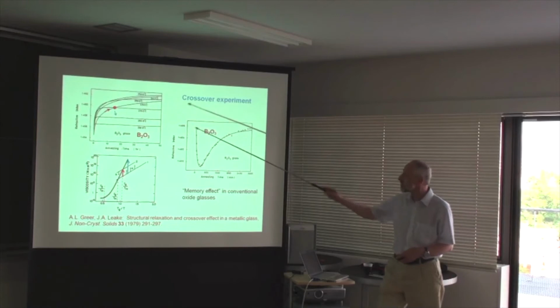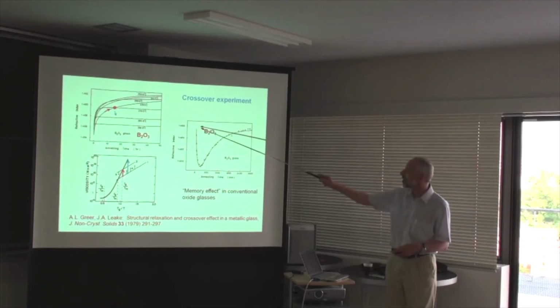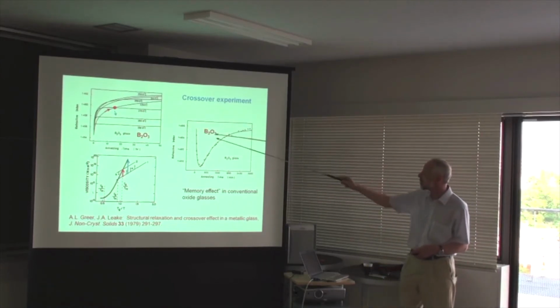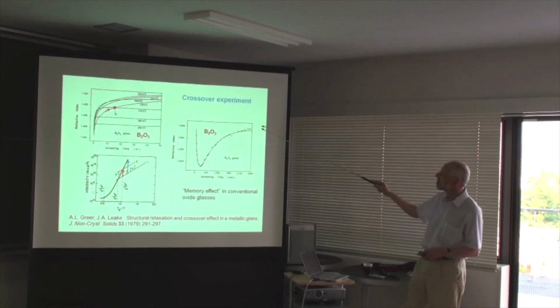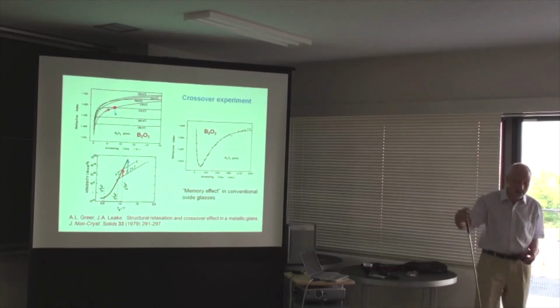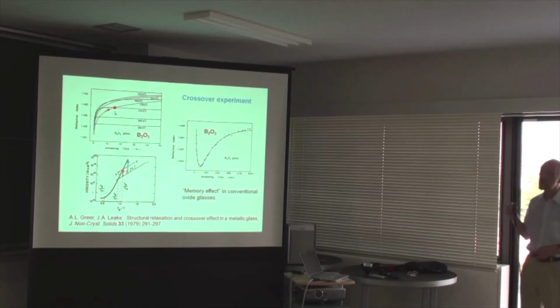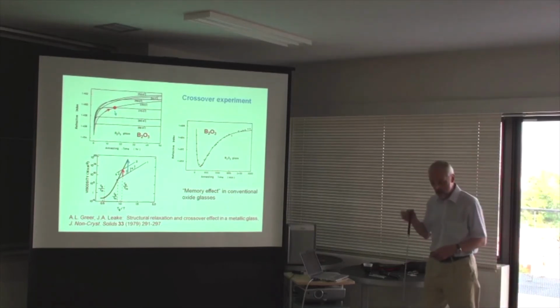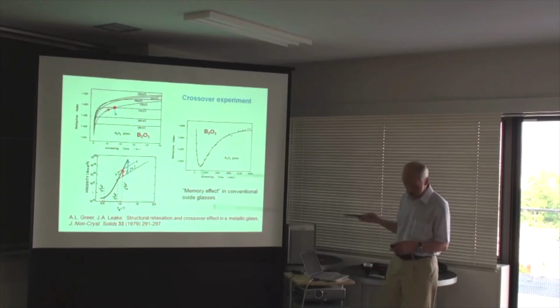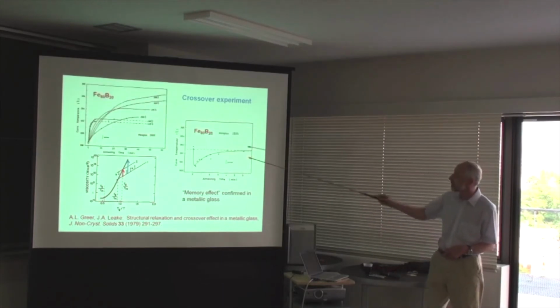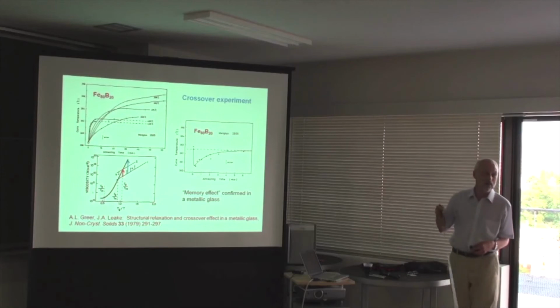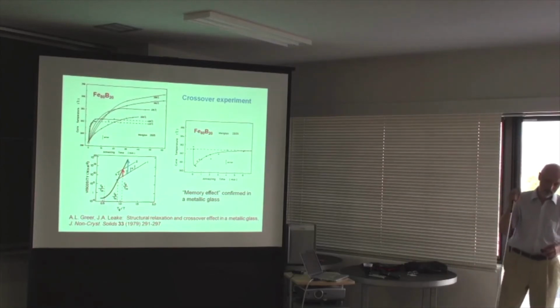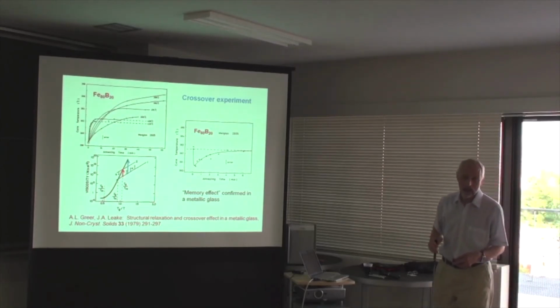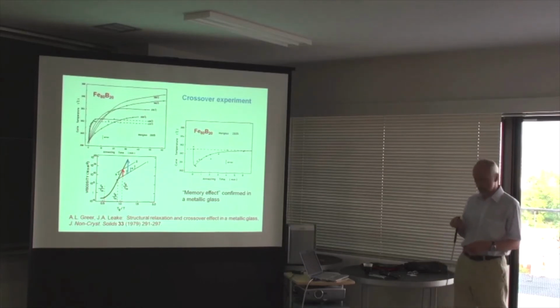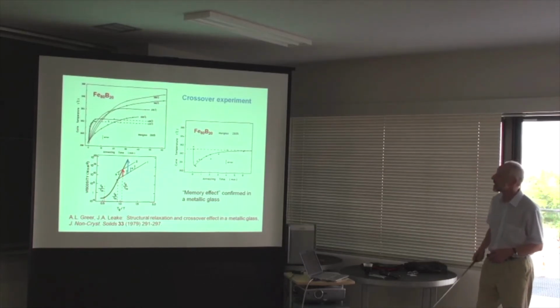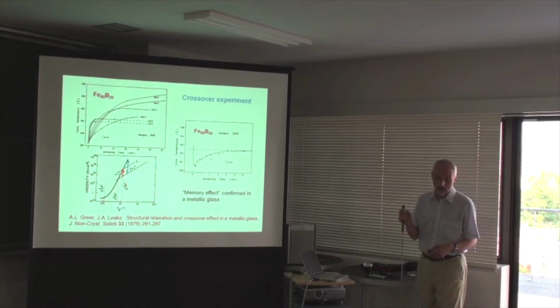If you take those two samples and you anneal them subsequently, one just carries on with the same value of the property, the other one goes through this strange thing where it appears to memorize an earlier structure, the so-called memory effect. And that was characteristic of glass relaxation for oxide glasses, and we were fortunate enough to be able to show that just the same effect shows up in the metallic glasses. So it was yet another little step along the road to saying that metallic glasses are real glasses in the general family.